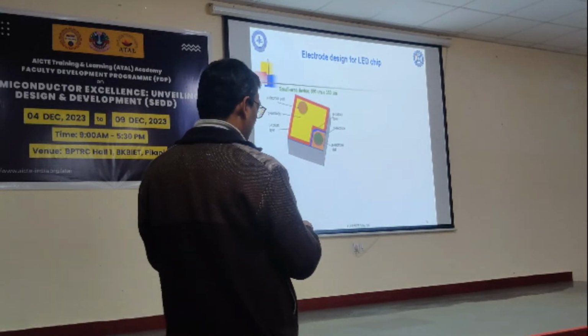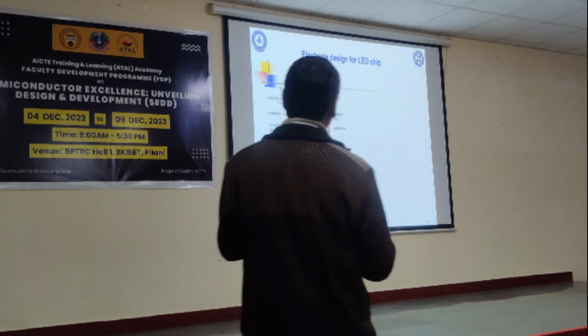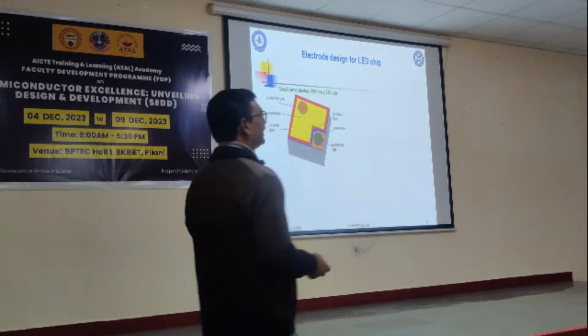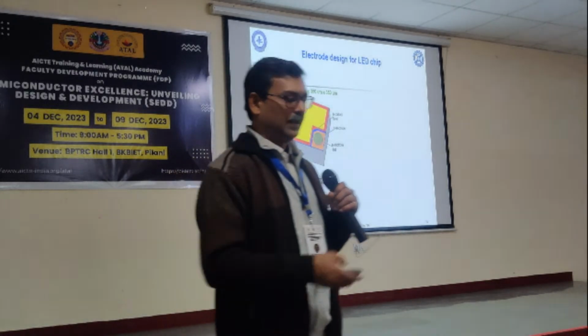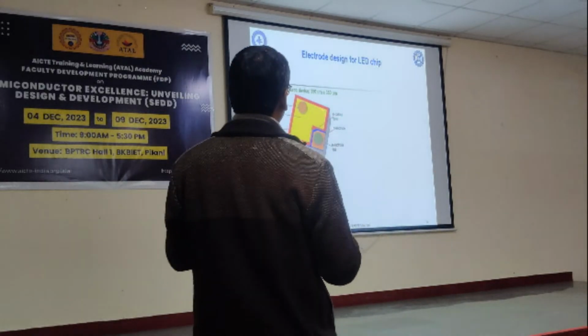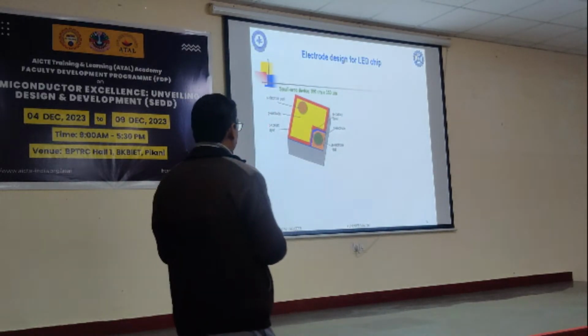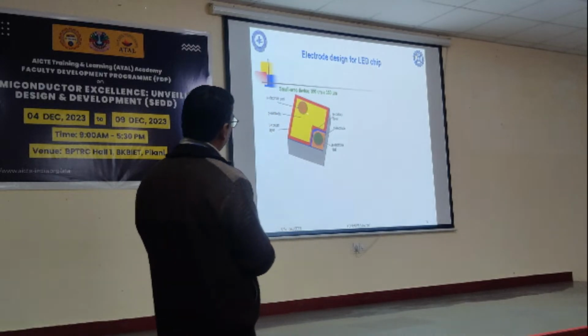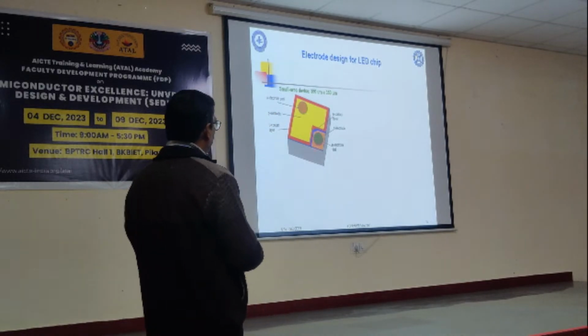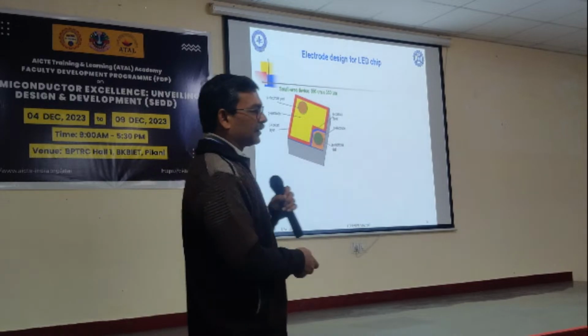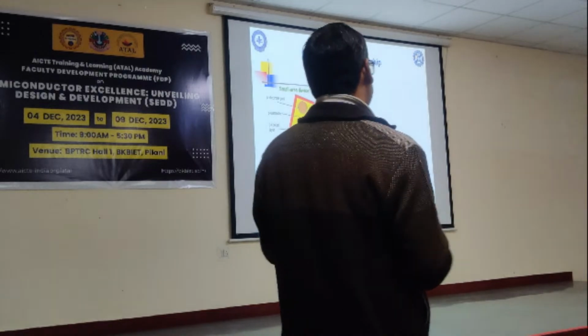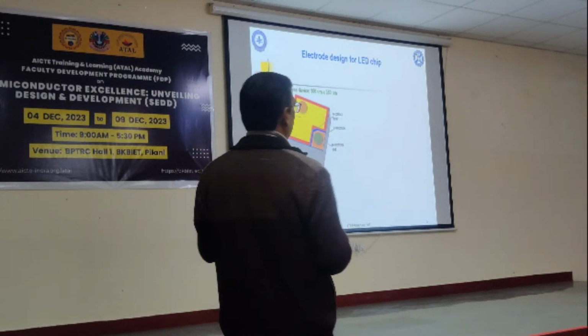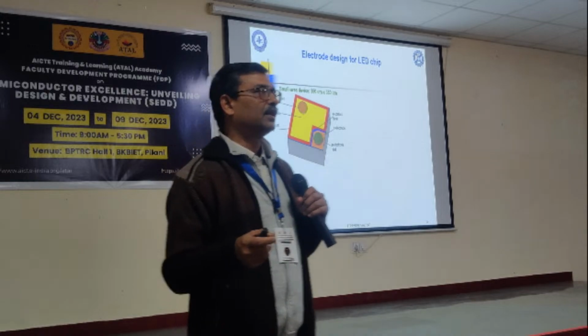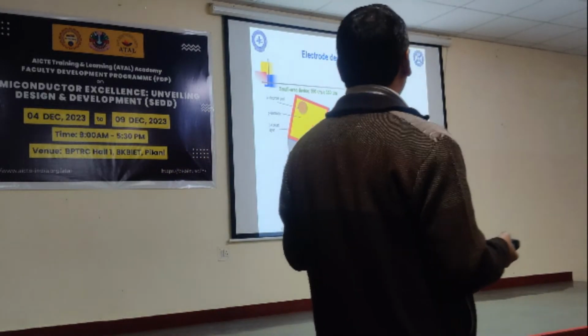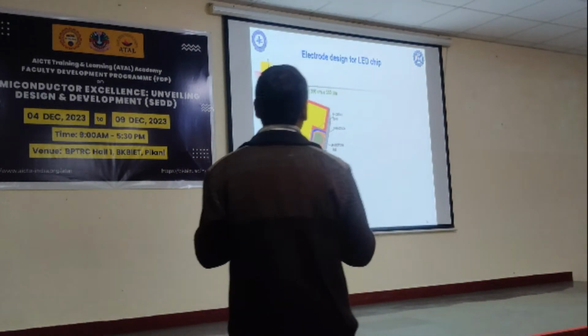This is called the pad type of structure. But if the device size is, in general, 1 millimeter by 1 millimeter, we cannot use this type of pad structure. In that case, what happens? Because current flows from that region to this region, and the current density will be much more in that area, and in between it will be very less. So uniformity of current density will not be there. If the current density uniformity is not there, then light uniformity from the emission area will not be there.